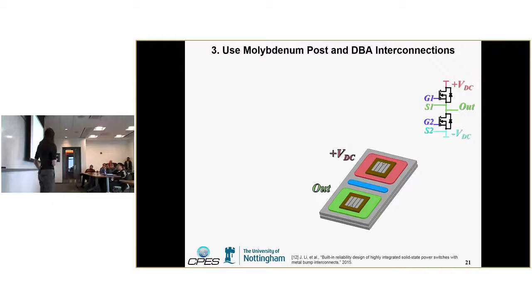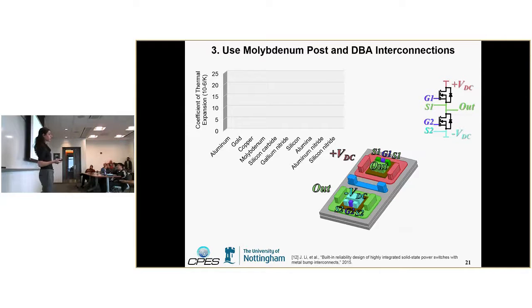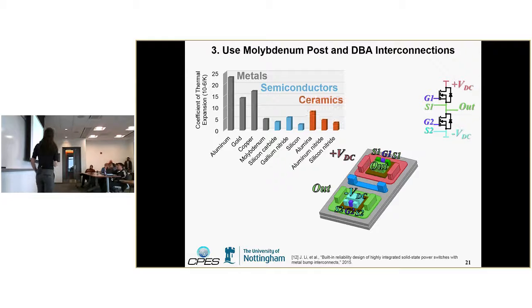Okay, and then for the interconnection, we're using molybdenum posts instead of wire bonds. The reason for using molybdenum is its coefficient of thermal expansion. Metals typically have a very high coefficient of thermal expansion, meaning they expand and contract a lot as temperature increases, whereas semiconductors and ceramic materials, the blue and orange bars, have much lower CTE. That mismatch causes a lot of thermomechanical stress on the devices and can cause reliability issues. So we're using molybdenum because it has a much lower CTE, very close to that of silicon carbide.